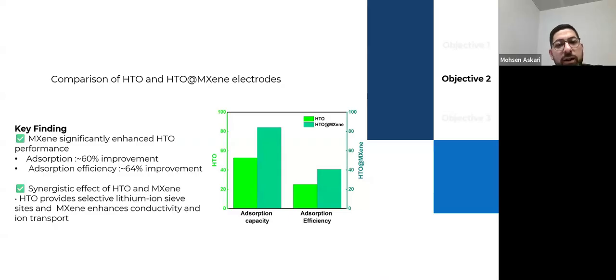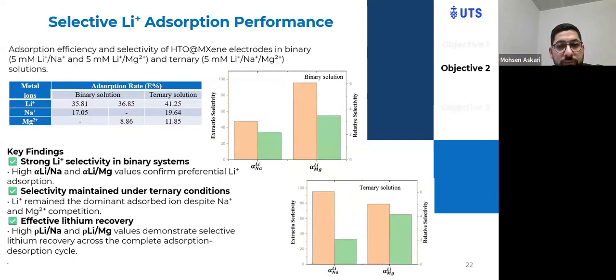We compared the HTO and HTO MXene electrode, and it shows that adsorption capacity improved 60%, and adsorption efficiency, meaning adsorption rate, improved 64%. It shows the synergistic effect of the HTO and MXene, while HTO provides the selective lithium ion sieve sites and MXene enhanced conductivity and ion transport.